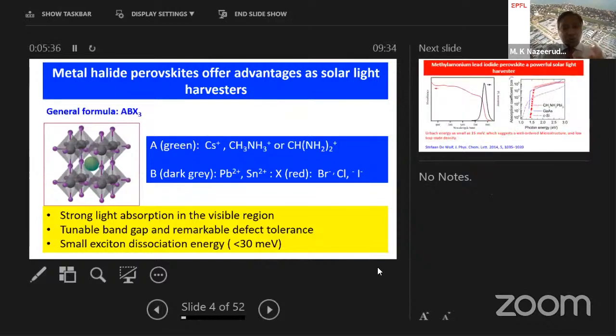So I highlighted three important properties of these materials. The perovskite absorbs the whole visible spectrum from 400 to 800 nanometers, and you can tune the band gap of these materials by changing the cations or halides, and they have a remarkable defect tolerance. Also very important is a small exciton binding energy, which is less than 30 milli-electron volts. What happens is when you shine the light, we create carriers, and these carriers are collected at the interfaces. So whatever we are doing by shining the light, we are creating free carriers rather than excitons.